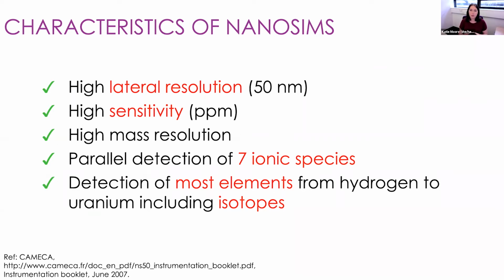Now, routinely, we typically don't image samples at 50 nanometer resolution because there's always a trade-off between resolution and sensitivity. So the NanoSIMS can actually achieve parts per million sensitivity for some elements, but we can't have that alongside our 50 nanometer resolution. So typically for a lot of our experiments, we're working in a range of between 100 and 200 nanometer spatial resolution, but that's still very good. It allows us to see, for example, subcellular information when we're looking at biological samples or distributions of elements at the scale of the microstructure.